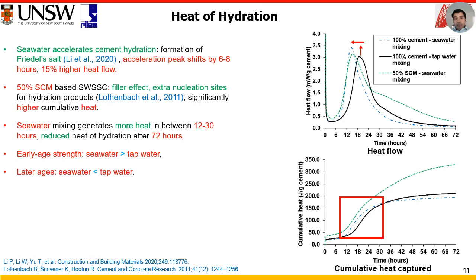To complement our mechanical test, we performed heat of hydration test and found that seawater indeed accelerates the cement hydration. Use of seawater not only increases the heat flow but also the acceleration peak has been shifted by 6 to 8 hours, which is an indication that seawater accelerates the hydration reaction. At the same time, use of over 50% SCM can significantly increase the cumulative heat, especially because of the filler effect and production of extra nucleation sites.